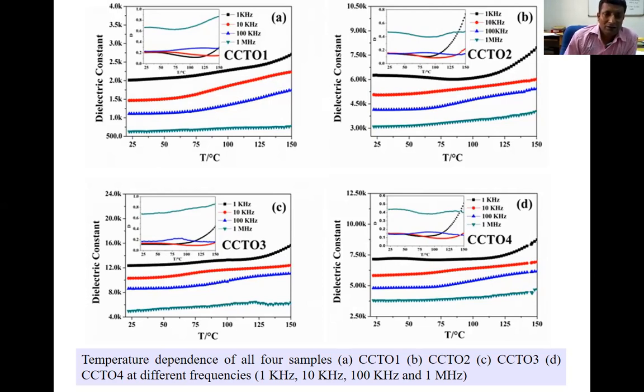Now, the whole plan of going for non-ferroelectric high dielectric constant material is because in ferroelectric materials there is a Curie temperature, and the maximum dielectric constant peaks near the transition temperature, the Curie temperature. If we want to use the ferroelectric material for capacitor applications, then the temperature should be near the transition temperature, because there the dielectric constant is highest. But near the Curie temperature, a slight variation in the temperature will lead to a drastic variation of the dielectric properties. And that is the biggest drawback of the ferroelectric materials if we want to use them for dielectric applications.